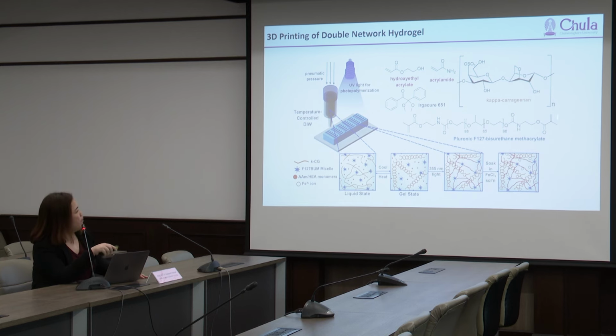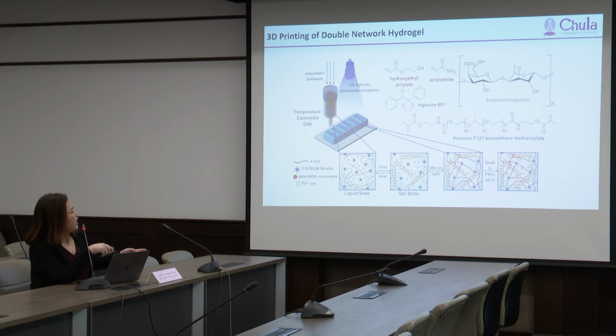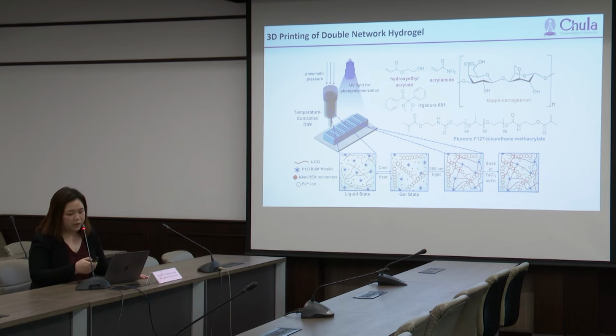So at first, we mix everything here in water, a crystalline surfactant solvent, at high temperature. And at that point, the F127 here will transform into the micelle structure. And then after that, when we cool it down to below 40 degrees Celsius, the kappa carrageenan will form the helical structure like this. So at this point, we can use this to 3D print and make a complex architecture. And then after we get the 3D printed structure, we shine the light, and this light can initiate the polymerization to cross-link the polymer network. And then after that, we soak that hydrogel into the iron chloride solution in order to incorporate the iron into the hydrogel.